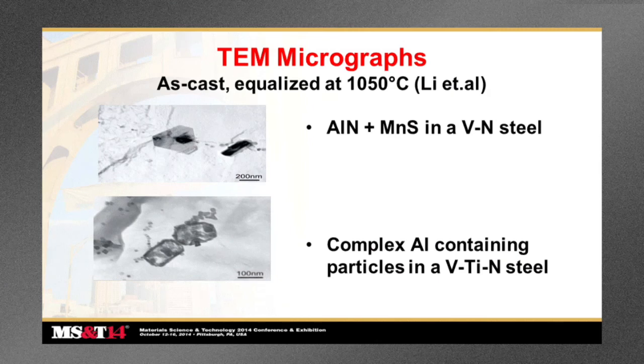This is an example of aluminum nitride formation in a vanadium nitrogen steel and also in a vanadium titanium nitrogen steel. The aluminum nitride will form, and at this point it's not contributing anything to properties. It does not provide a grain refiner because the grains are already large in this case, and it steals nitrogen away from the vanadium nitrogen system.